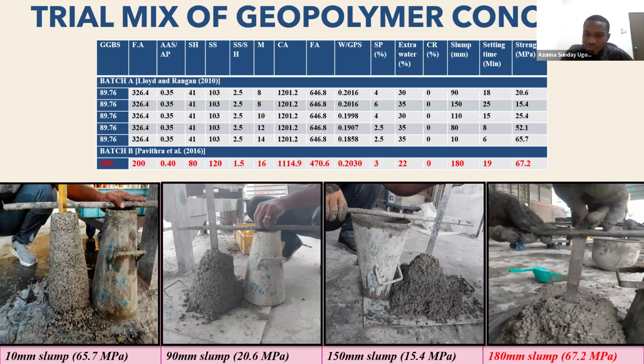By the way, in my project, I'm casting a column, so I needed a very high workability, above 150. In the course of my trial mix, you see the slump is 90 and the strength is 20 MPa. It's very low. Then when I tried to increase the slump to 150, the strength went down again to 15 MPa, which is also very low.